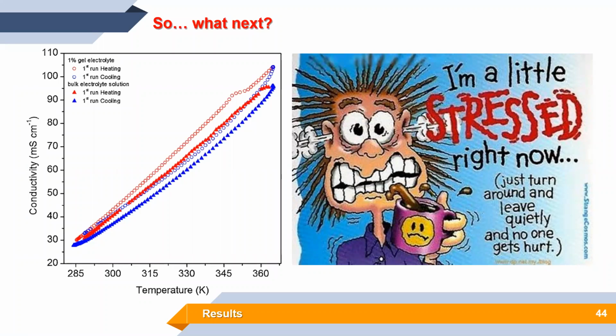So then we started to think what actually diffuses in the system and what this slow surface diffusion coefficient applies to. And it occurs that it applies to the molecules of the solvent, water or other solvent, but not to the ions themselves. So we have a situation where, in contrast to the liquid state, a part of the solvent molecules is, I would even say, hindered, because with 5 orders of magnitude slower diffusion, we can say that they are almost like static molecules at the surface compared to those in the bulk, diffusing very fast.